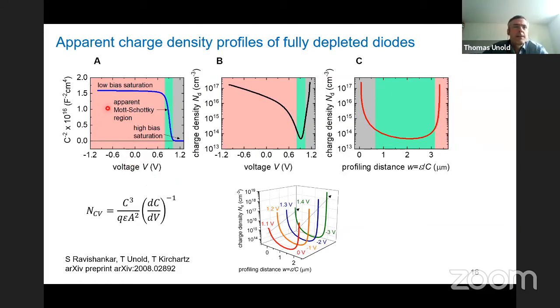So here, this is now from the SCAPS simulation shown again. This is 1/C² shown over applied voltage. So here, if it's a device in depletion, basically, we said very low doping, if you change the bias, it doesn't change much. Capacitance stays the same. And at some point, it increases. So 1/C² goes down, and then it increases a lot, and it goes to zero. Now, if you take this derivative formula and plot it versus voltage, it looks like this. Yeah? And now, if instead we plot it over the space charge region, it suddenly looks like this here. And that shows you now that this is kind of a universal shape you get here, which on this side is limited by the width of your device.